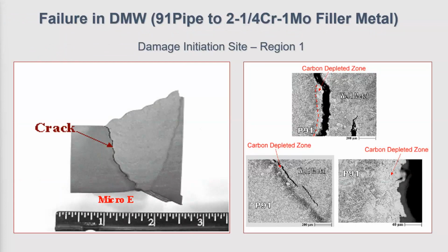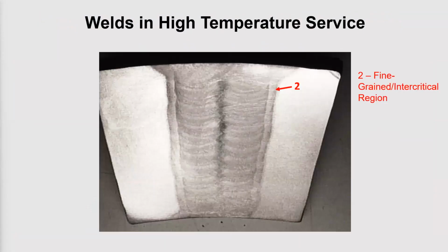preferentially decarburized. The carbon actually diffused out from the 2 1/4 chrome material to the grade 91 material, the 9 chrome material, and left a region in the weld metal adjoining the fusion boundary that was uniquely susceptible to damage because it had basically been decarburized. Now, there are some other issues with this that we'll talk about later, but the important thing here is the location.